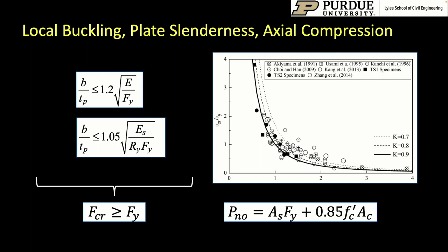At the same time, we also did provide an equation for estimating the F critical or the local buckling stress associated for the steel plates, and we provided equations for estimating the axial compressive strength of the steel plate after the concrete has been cast. So we started off by looking at the detailing of the tie bars before the concrete has been cast, and then we ended up looking at the slenderness of the steel plates after the concrete has been cast.